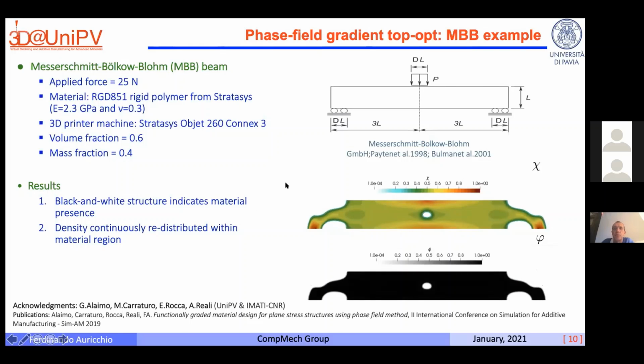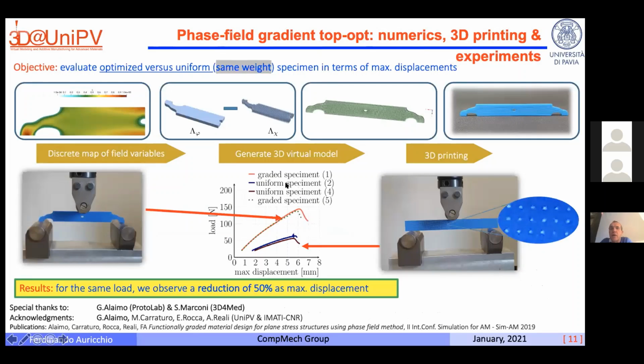And the very nice thing with additive manufacturing is that you can also produce your component and you can do experimental tests. So once we run our numerics, we also develop some computational steps in order to end up with a component, which you can see here, where you can a little bit see the internal structure. So you can see that in certain regions you don't have the material, but in other regions we have a graded structure. And the very nice thing is that we did experiments, and basically here on the right you can see the structure which is uniform as a material.